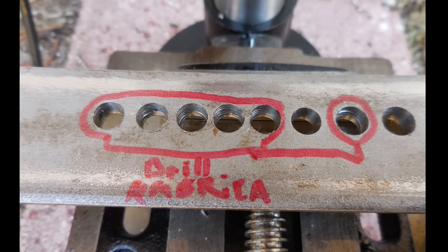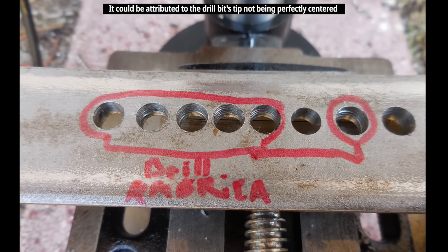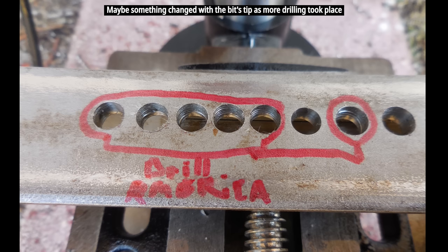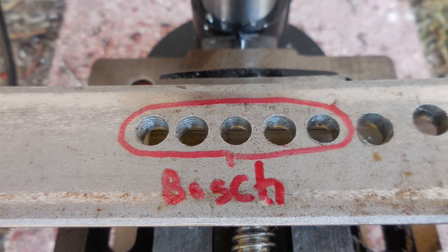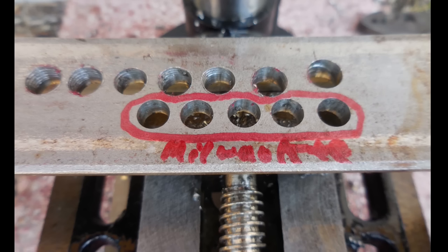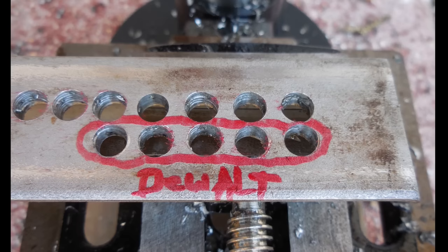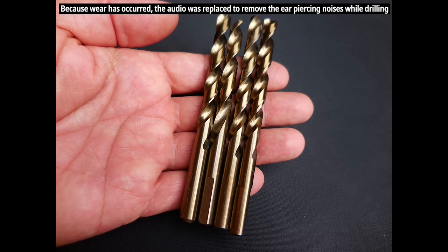Right here you can see the Drill America holes, all five lined up. You see the first one we drilled on the far right. The Drill America holes still have a lot of horizontal lines or grooves inside the holes. The first hole on the left was the last hole that was drilled of the five. Very interesting that that one's smoother than all the others. For the Bosch bit you can see the first hole on the right was the second hole to be drilled. And as we drilled more and more holes to the left, to the far left, you can see there was a lot more grooves, very similar to the Drill America. Right here are the holes created by the Milwaukee Red Helix bit and you can see how beautiful each one of those holes are. They're very smooth and as the bit was drilling in each one of those holes, we had really nice continuous metal shavings. And the last one is the DeWalt bit. You can see the inside of each one of the holes that were drilled is fairly smooth. There are some horizontal lines inside the holes but not nearly as much as the Drill America bit. Now we're going to drill one final hole and we're going to time how long it takes for each one of the bits.